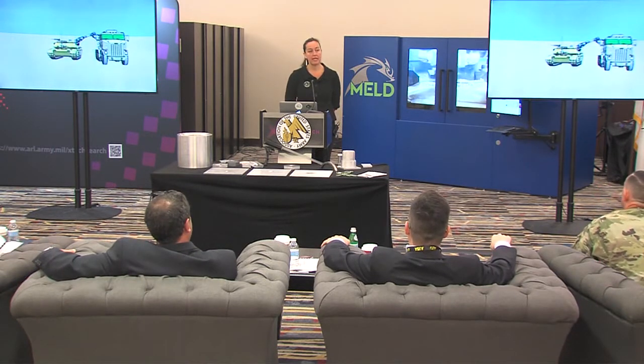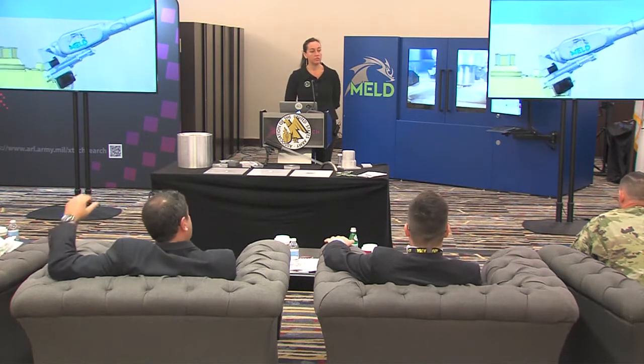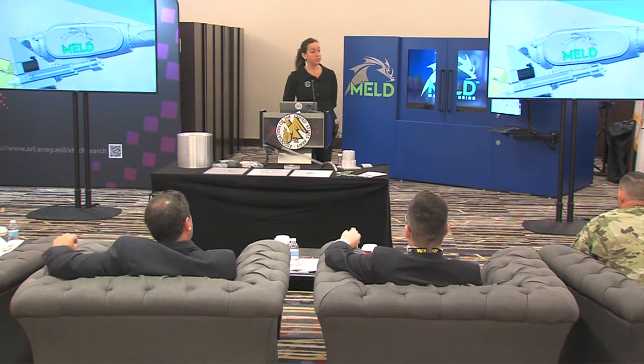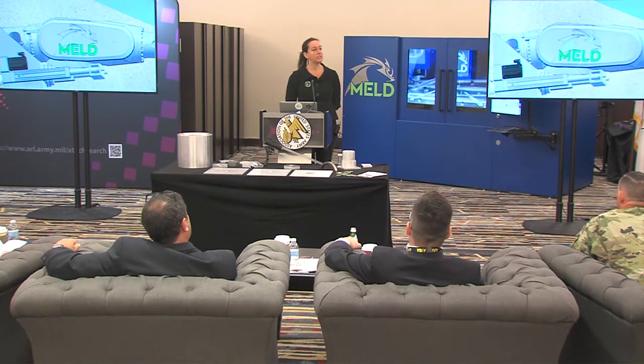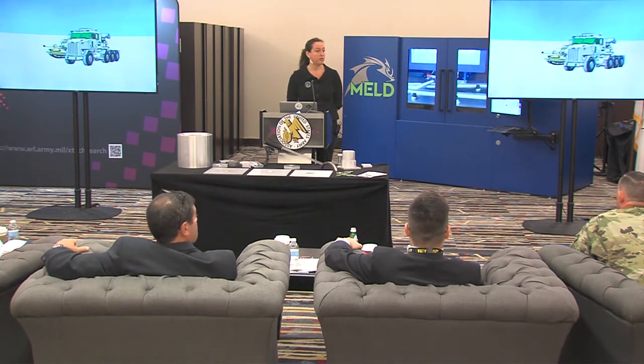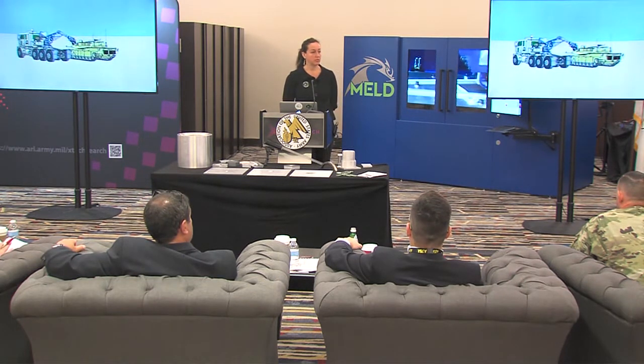I was wondering about the surface temperature when you're doing the application of magnesium. When you were building the magnesium part, did you measure the temperature of the material? In all cases, the temperature of the deposited material is going to range between 60 and 80% of the melt temperature. That's a good rule of thumb. There are opportunities to control temperature if there's some desire to do that. And we do have the ability to control ductility over strength, for example, in that way, if needed. But in all cases, you're going to see about wrought properties from the melded material.